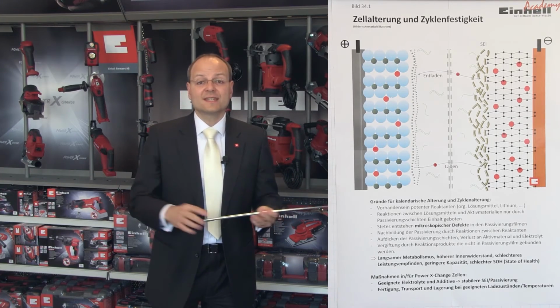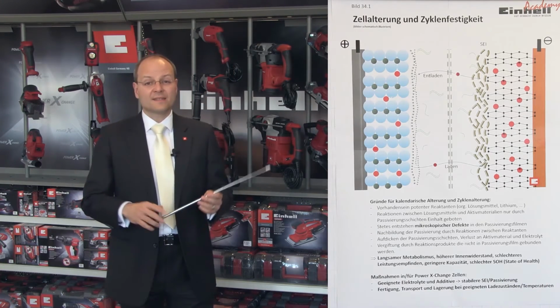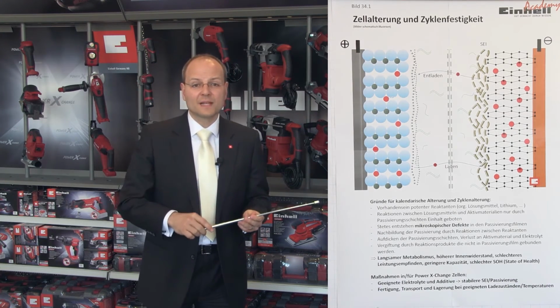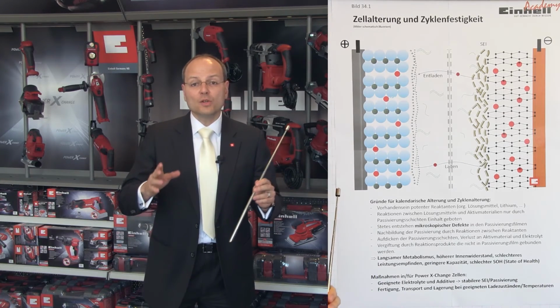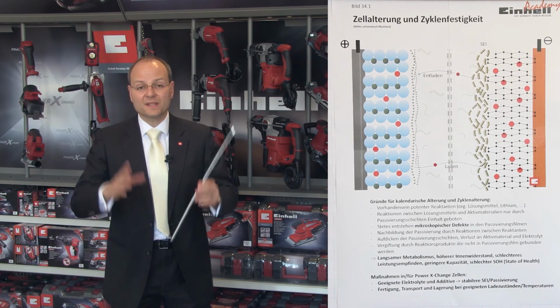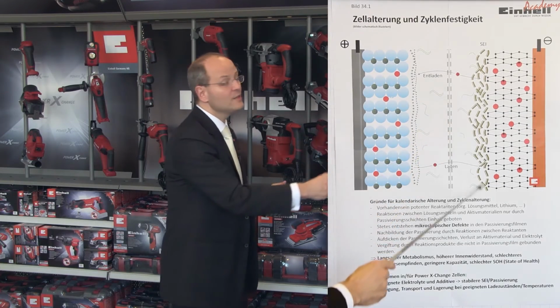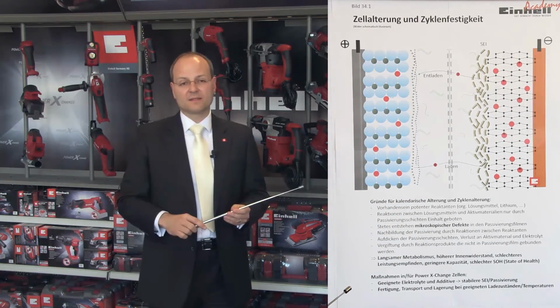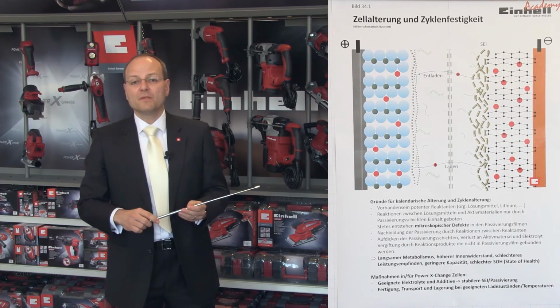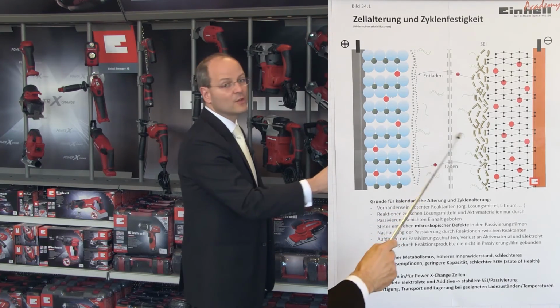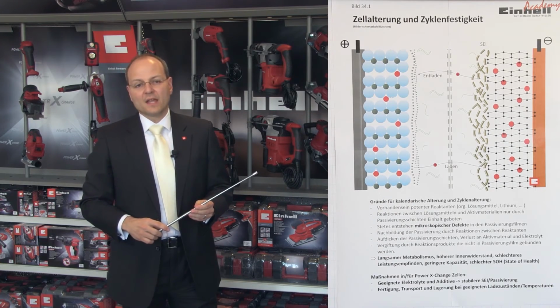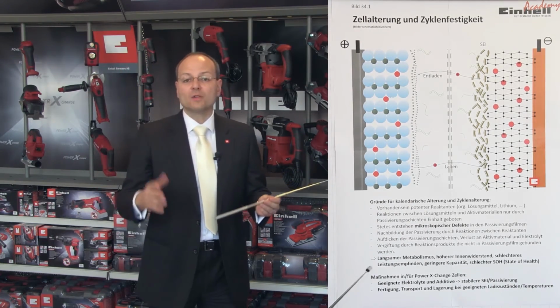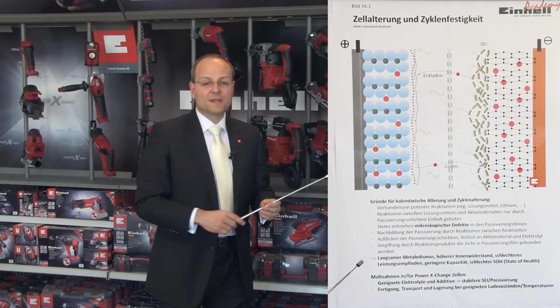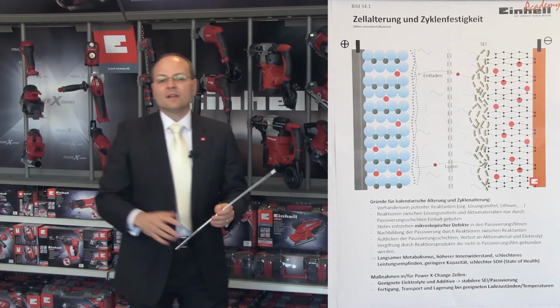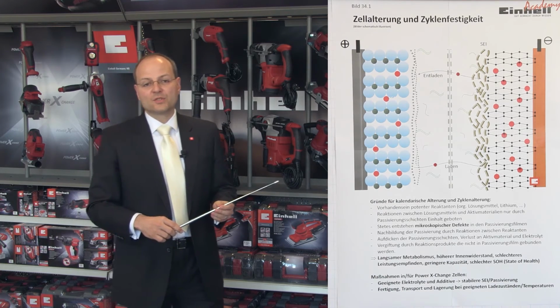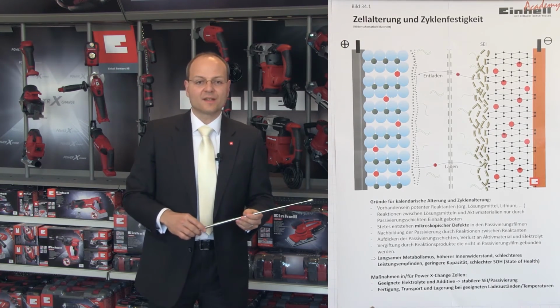We suspect that the main reason for this intrinsic cell aging is linked to the high reactivity of the organic solvents in the electrolyte, which can only be held in check through the technical formation of passivating surface films on the active material. Over time, microscopic defects will always occur in the passivation, which are then recreated. In the process, electrolyte, active material and lithium are lost. The thickened passivation films gradually become impermeable to the positive lithium ions, and the resulting reaction products interfere with the regular function of the cell chemistry.